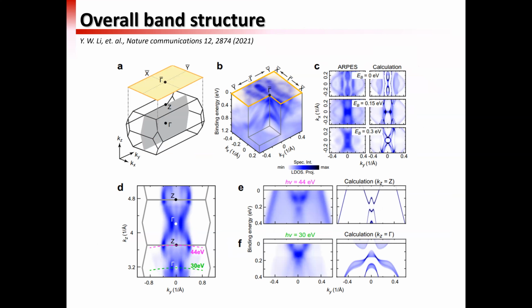And here, I don't think I need to go into the details of the bulk structure, other than saying that it's quite ARPES friendly, and our measurement is of high quality. We can compare the result to the calculation one-to-one, and they show very good overall agreement, right? Both in the constant energy map as well as the band dispersions. And this gives us confidence that if we see something different from the bulk states, then it should be surface, and also that our calculations should be reliable.